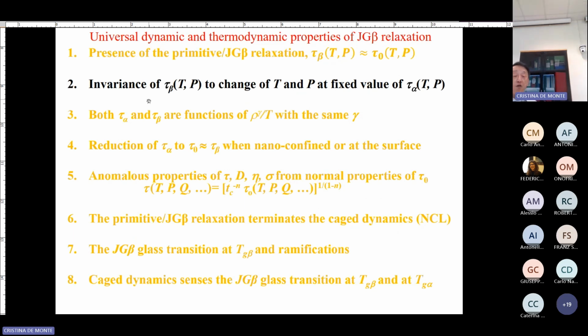The next one is very cute. This is the invariance of the Johari-Goldstein or beta relaxation to changes in pressure and temperature at a fixed value of tau alpha. So you do an experiment, you choose the pressure and temperature, and you can vary the combination, but you keep the alpha relaxation time constant. That's easily done experimentally. And then you look at what the tau beta is doing. If you keep the tau alpha constant, does tau beta sometimes change, sometimes go there? No, it turns out they always keep the same relation.